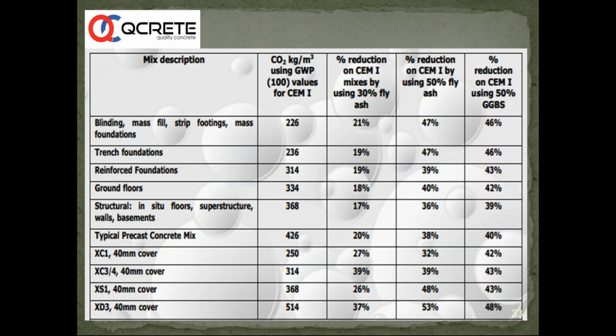Whereas if you are moving towards 50% Flyash or 50% GGBS, it is almost reduced by 38 to 40%. There is a reduction of global warming potential over 100 years by 38% to 40% when we are talking about usage of Flyash 50% and GGBS 50%. Even when you are using 30% of Flyash, the reduction is about 20 to 30% on various types of concrete. So this is a very, very important table actually, which talks about the environmental impact. And we can see that we need to try to use as much Flyash as possible based on this table.